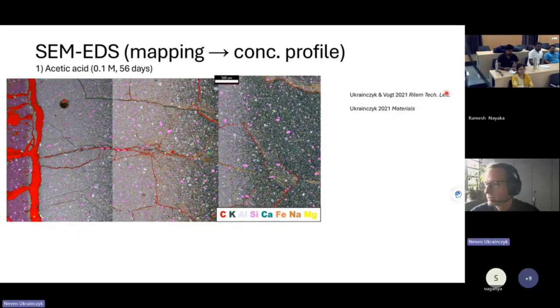This was an invited paper. Basically, because this was cement-based, you have to do the cross-section because you are interested in the depth. So this is the cross-section. And then you have to polish it. No, first you should impregnate in epoxy because you want to preserve exactly the microstructure. So we impregnate it with epoxy.